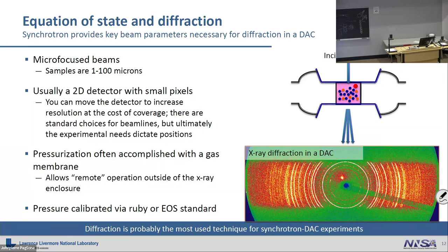The worst thing you can have is the one that's in the middle, which is not a good crystal and not a good powder, but as you go to higher and higher pressures, that's what you end up with. Because your sample volume gets small, you only have N crystals in there and N is not 10 to the 20. And so you end up with a lot of these spotty patterns that she talked about before. And there's a lot of work going into how to analyze that now, how to actually push your software to do that kind of multi-crystal scattering instead of powder diffraction or single crystal scattering.